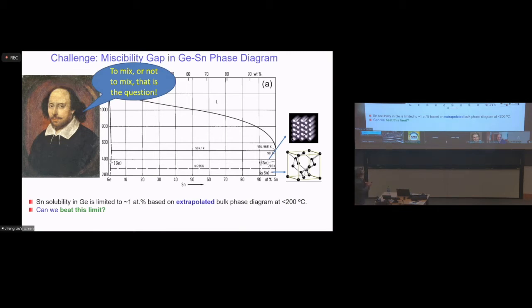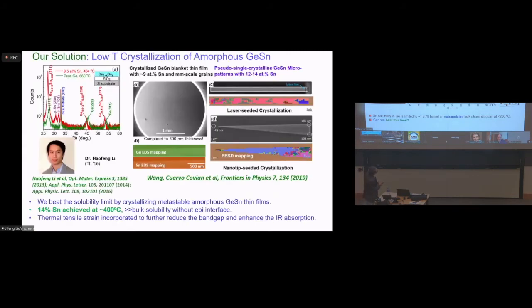Actually, you do, because tin at higher temperature has this metallic structure, an tetragonal lattice, and at lower temperature it has the diamond cubic lattice, which is the same as germanium. So maybe you can play some tricks here. The trick we play was first demonstrated by my previous PhD student, Haofeng Li. We deposit amorphous layers of germanium tin, so the unit cells are not aligned. They have random orientations. It's a metastable, high energy state.